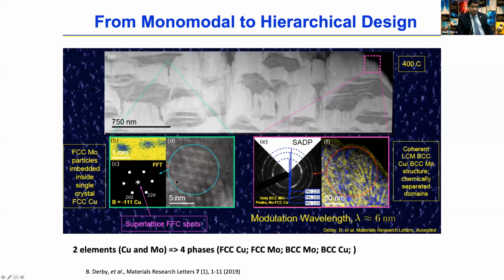And that is shown in this high resolution STEM image. Those brighter regions are moly atoms that have clustered in the form of an FCC structure. So the moly-rich phase has become face-centered cubic. It has precipitated inside the copper island, and it has formed a metastable structure. It has also formed a periodic array in 3 dimensions to the point that you can pick up diffraction spots from the superlattice. All of this has happened by itself during deposition.